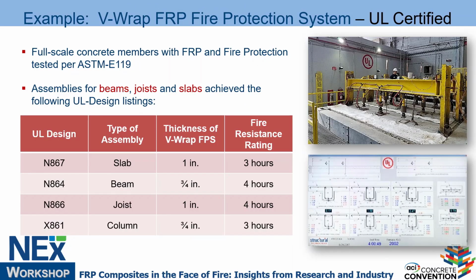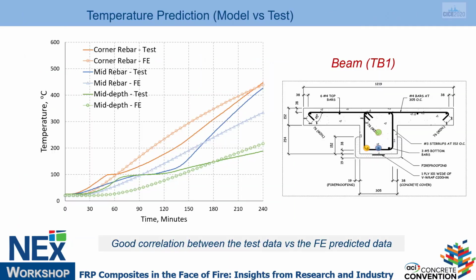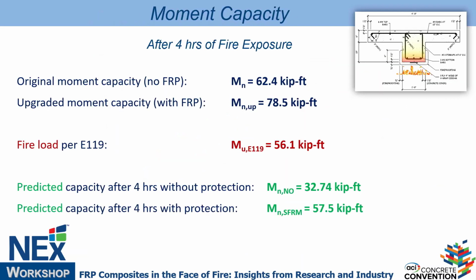And this is one example. This is a system I mentioned. 1 inch, 3/4 inch can give you up to 3 or 4 hours. And some of these tests I mentioned at UL, we actually instrumented them with thermocouples on the FRP location. The concept is we needed this as a data point to show building officials that we can predict the capacity. We don't need to do the test all the time. So you can see here the thermal modeling, and again, the lines are not exactly on top of each other, but relatively good accuracy. It's actually more on the conservative side. And we can use this to calculate the capacity.